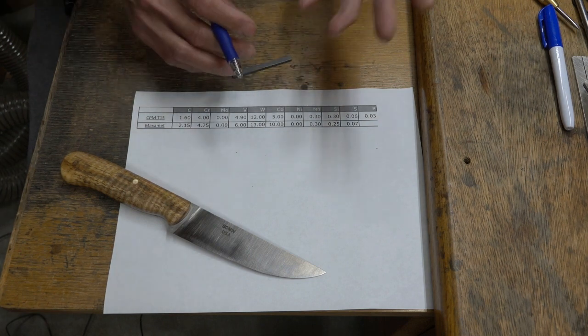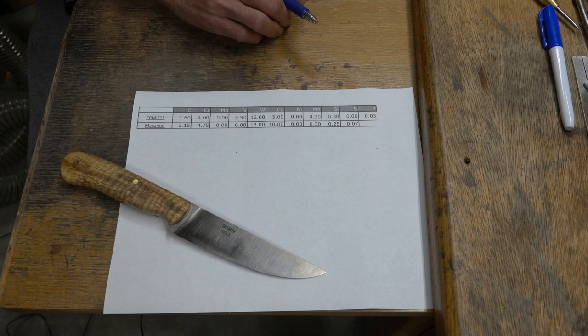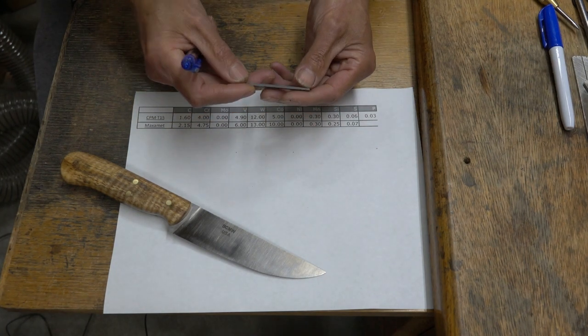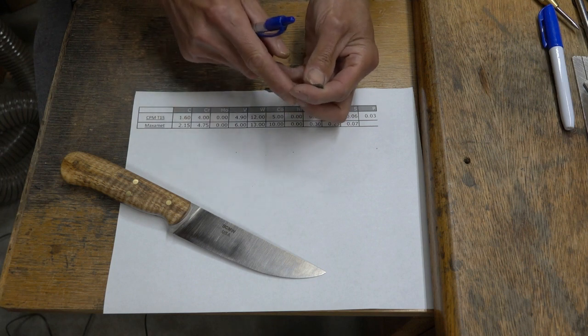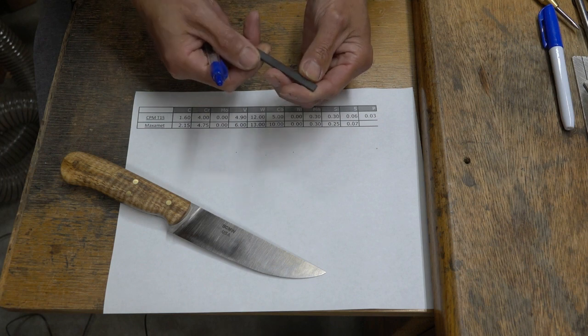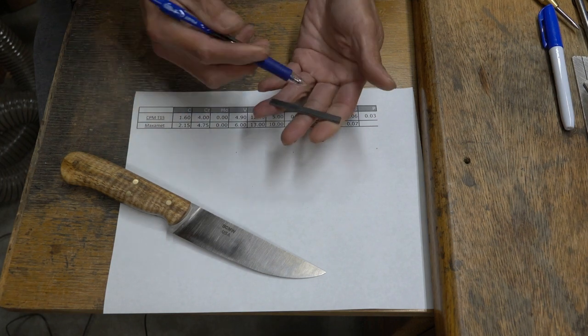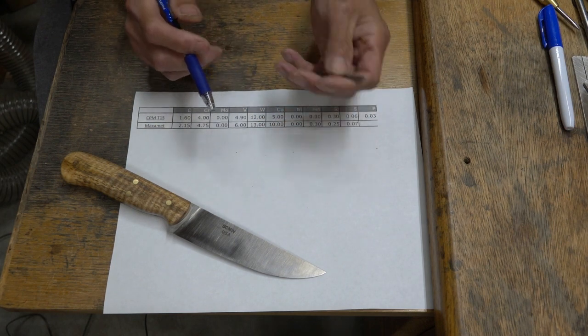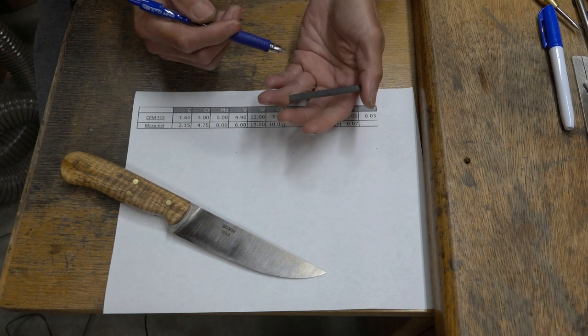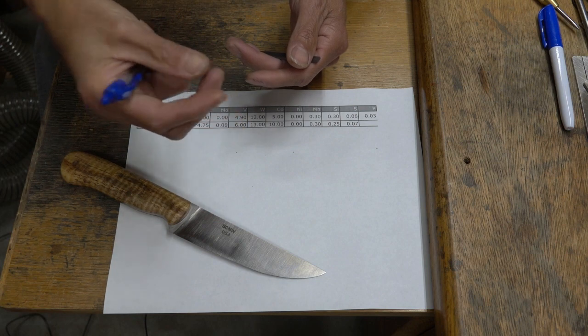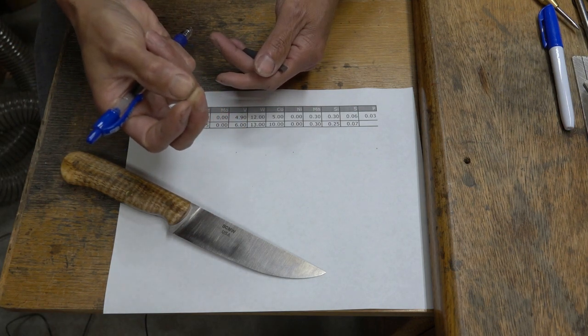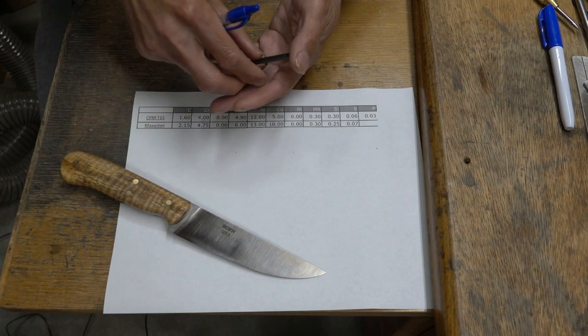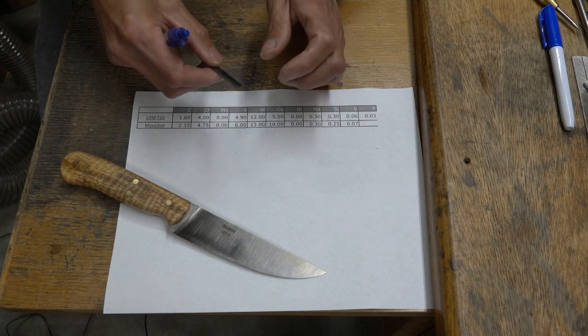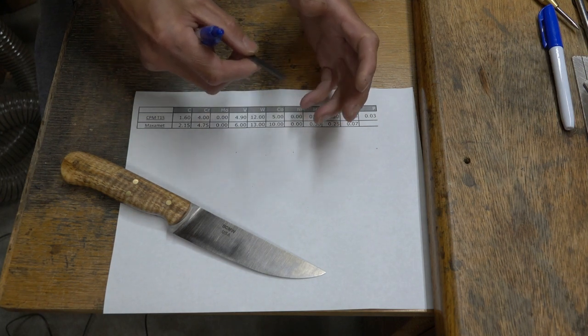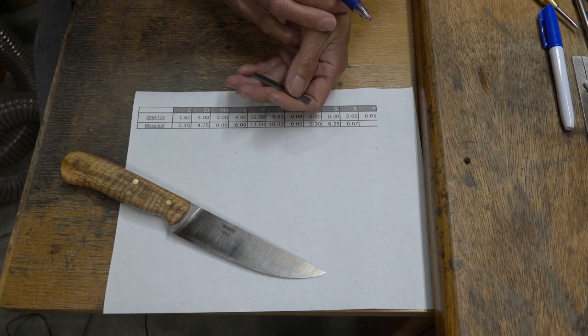So this is a conversation here. This is a carbide scraper at a 60-degree angle here, and most carbide tools, whether drill bits or scrapers, have about 10% to 15% cobalt. The cobalt is the matrix that holds the little particles of tungsten carbide in place. If you had nothing but a cobalt matrix, the Rockwell hardness equivalent, when you tested that matrix, would be somewhere around 40 HRC.